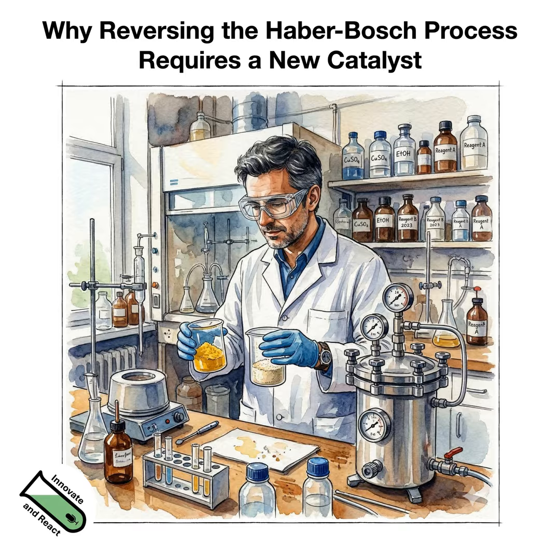The other challenge would be the dehydrogenation of the ammonia molecule, which is like the early barrier that needs to be considered, and then the late barrier in the mechanism would be the nitrogen recombination. Yeah, those barriers are important. And to have the most efficient round trip, basically from hydrogen to ammonia to hydrogen, we want those barriers to be the smallest, and therefore the best catalyst available.